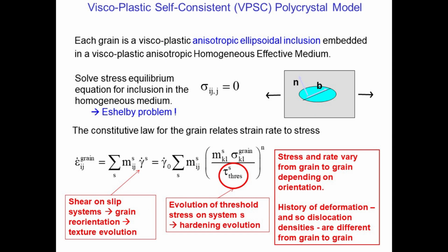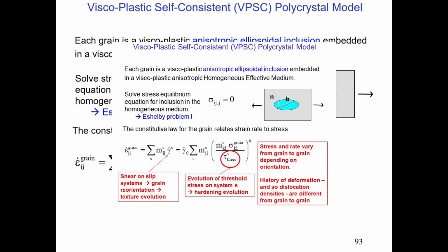So that is essentially the tau threshold that we are going to put in our law. I showed this slide before. The tau threshold that is going to go into our law is the tau intrinsic plus a correction to it because of the presence of reversible dislocation.